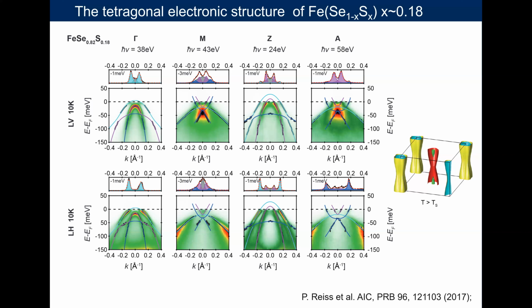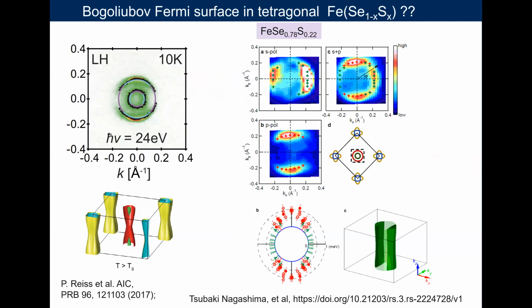Now, this type of Fermi surface in the tetragonal phase has been suggested to harbor Bogoliubov quasiparticles, Bogoliubov Fermi surfaces. I just wanted to show here what has been recently reported using laser ARPES. When you measure with laser ARPES, you have very high resolution. However, you can only probe a very small region of momentum space, often at the gamma point. So here is laser ARPES on tetragonal iron selenide sulfide, in which a strong anisotropy of the gap and the formation of Bogoliubov Fermi surfaces inside the superconducting phase is being claimed.